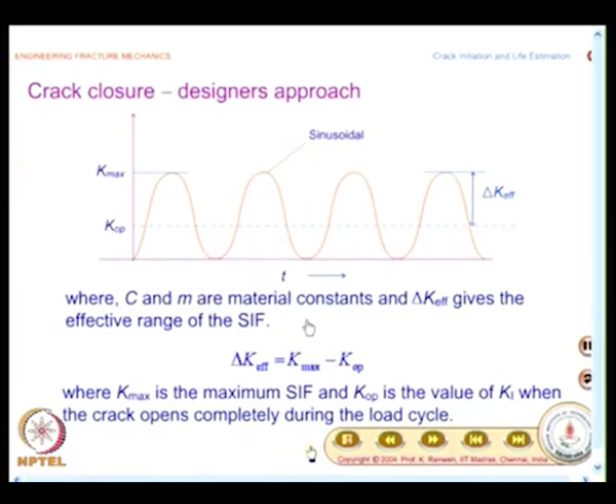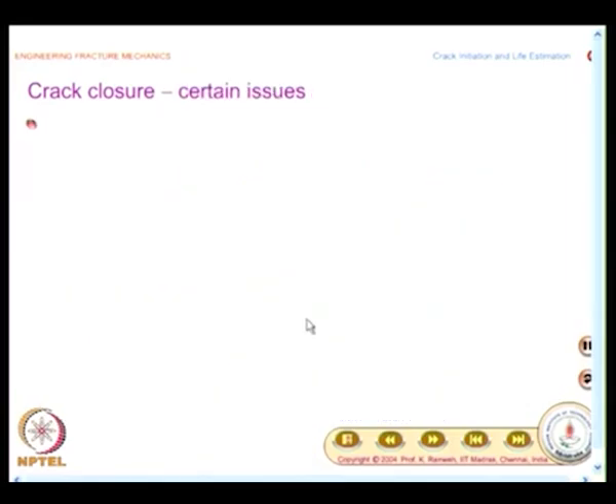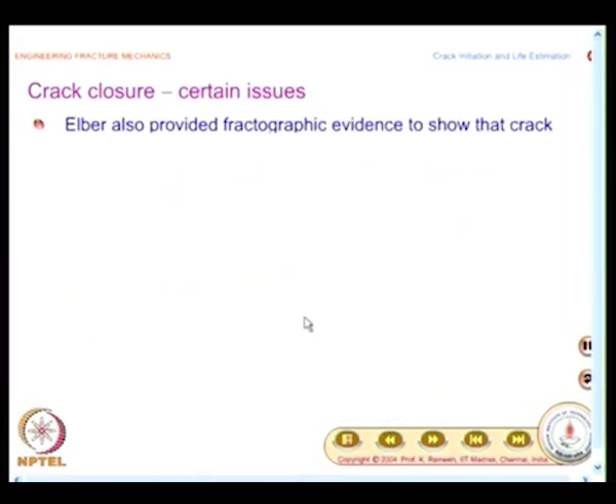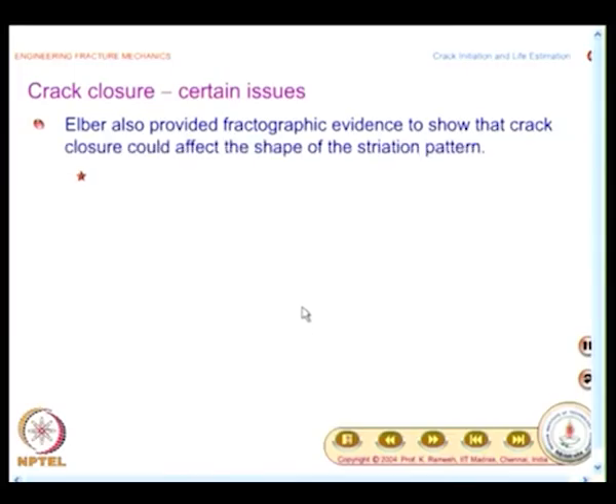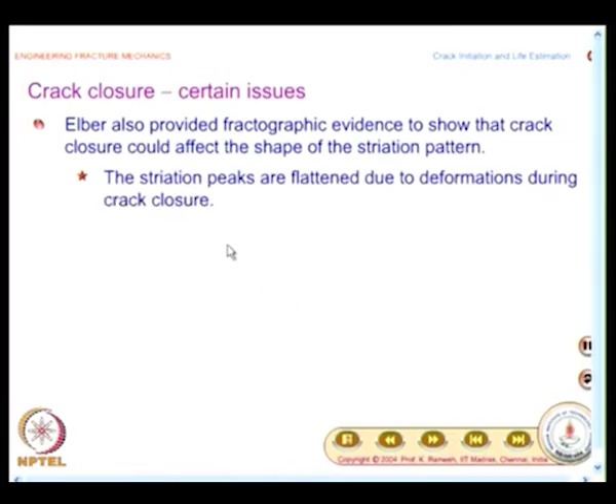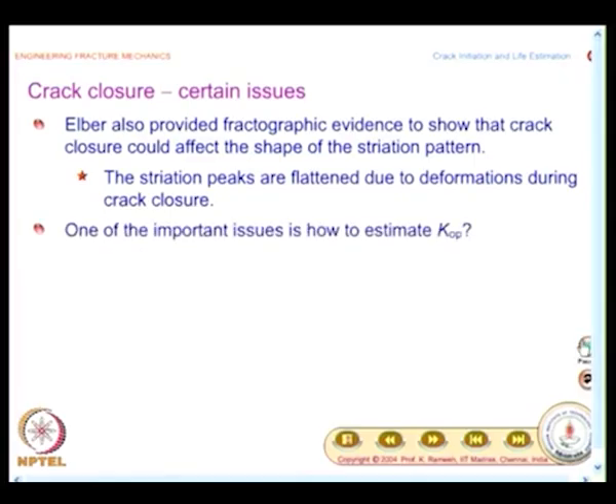There are empirical relations reported, and in order to ensure that crack closure indeed happens, Elber also provided fractographic evidence to show that crack closure could affect the shape of the striation pattern.